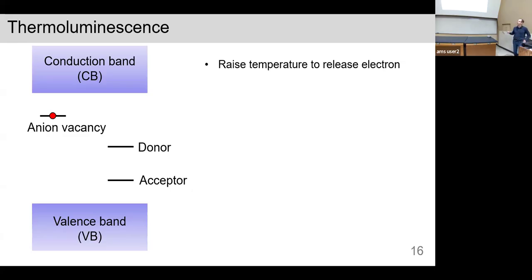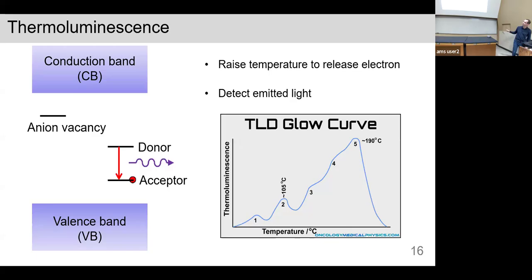So we have this anion vacancy, like a chlorine vacancy with an electron, and it's stuck at room temperature. But you can raise the temperature to release that electron. And it might go up, it might go down. But when it goes from this level of an impurity to this level, different impurity, it actually emits light. So you excite the electron up here and somewhere it gets captured and then falls down, and to conserve energy, a photon is emitted.